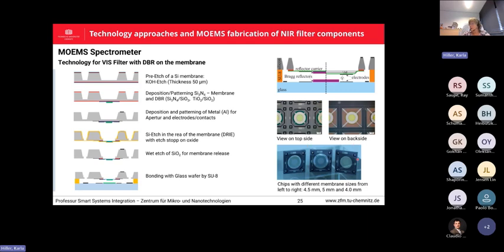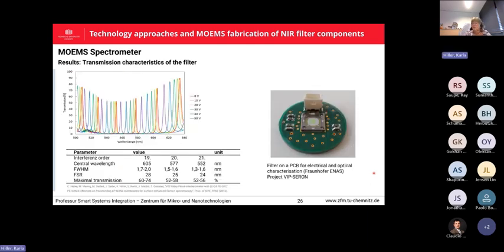Yeah, you see here some pictures of the realized filters with different membrane sizes, different membrane configurations. And we can also see here, we have really prototypes of the tunable filters. And in this case, it was designed for central wavelengths around 577 nanometers, and especially with the target to have a very small bandwidth in the nanometer range only. And this means we have to use a very high interference order to get these very good results. This means, on the other hand, that the free spectral range is very small. You see this at the lines of the same colors indicate this free spectral range.